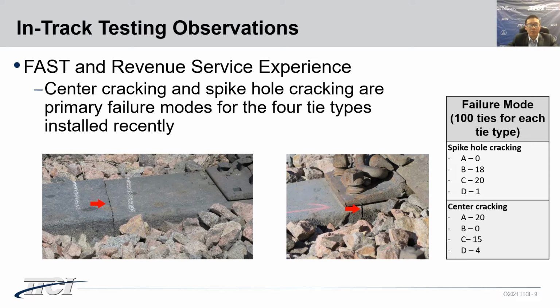Spike hole cracking was the other common failure mode observed. Spike hole cracks were generally observed to develop after tonnage accumulation and have not been observed during laboratory spike insertion and pull-out testing. All of these ties meet the AREMA recommendations of laboratory tests. This indicates that current testing recommendations do not adequately assess the performance of composite ties to address these 2 failure modes. For this reason, we are developing laboratory tests to better address these issues.